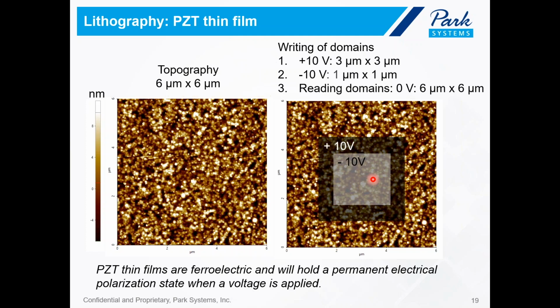To read, we will zoom out to a 6 by 6 micron area, because we want to include all the previous scanned regions, and we want to have some reference point. So we scan a larger region that is outside the 3 micron by 3 micron and 1 micron by 1 micron scan. In this case, we don't apply any DC bias to the tip. So 0 applied DC bias.